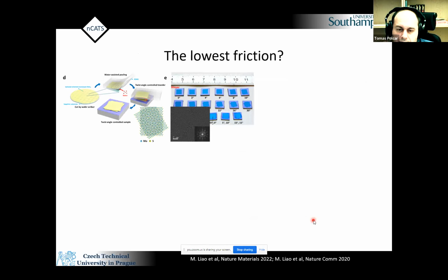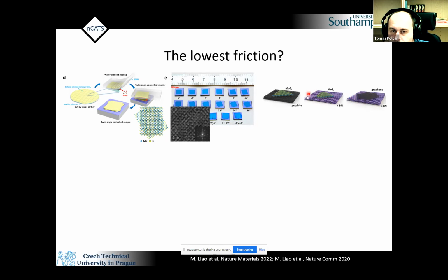First, how to prepare the material. It was the work of my postdoc, Meng Zhao Liao, and he did a fantastic job. First he developed the method and improved the method of water-assisted peeling, which allows him to produce various heterostructures rotated with really well-defined angles. Once you have that, he was able to provide systems with heterostructures of graphite and molybdenum disulfide, or hexagonal boron nitride, or molybdenum disulfide with other combinations, graphene and boron nitride.